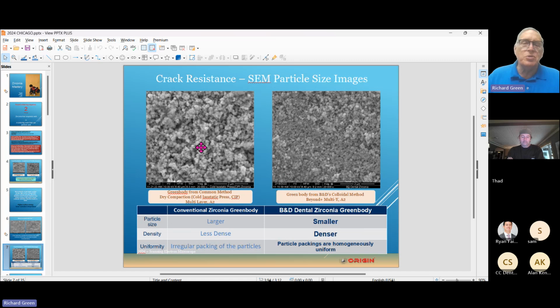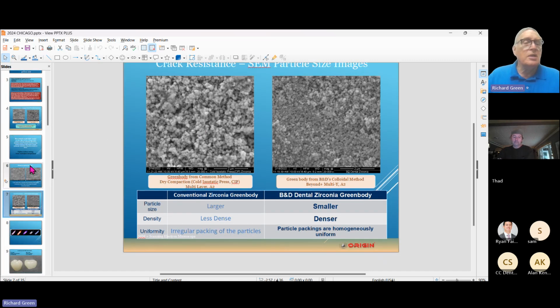That means they're going to respond to the temperature changes in the 1 hour firing cycle that we use. So what we've got is for you to take advantage of a 1 hour firing cycle, or for an all on four now, as fast as about 3.5 hours. This means that you guys can choose to use things. Now, your conventional sintering may work for you just fine, but by having the opportunity to sinter things faster, you have another tool that can give you greater control over what's going on in your laboratory.